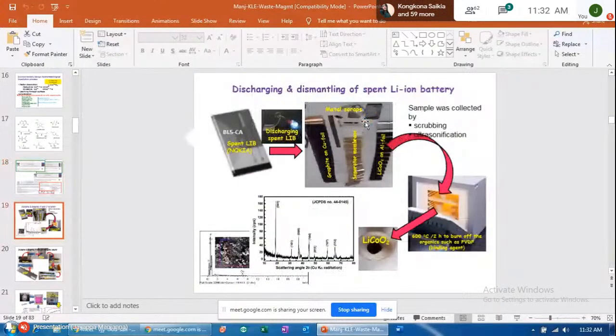Here is the methodology to share with you. We take a spent lithium-ion battery and discharge it completely, because you all know there is short circuiting and fire, which you must have read about several times. This is all due to short circuiting of the anode and cathode materials in the lithium-ion battery, because in between there is a polymeric membrane for ion transport. If it undergoes damage, there is a short circuit. Therefore, one should be very careful.